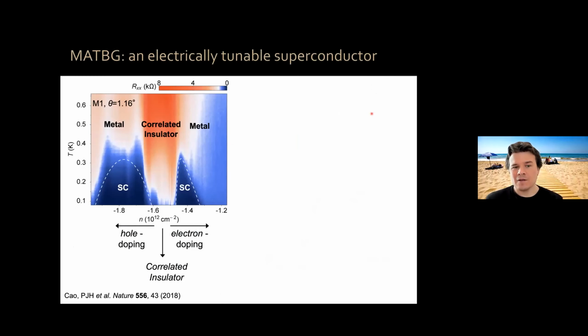Now, magic angle twisted bilayer graphene is an electrically tunable superconductor. In our devices, we have the magic angle graphene, and we have a nearby parallel metallic plate, so that we can make a parallel plate capacitor, and by applying a voltage, change the charge on the plates of your capacitor. One of the plates is the magic angle graphene. One of the interesting things about the system is that you have a correlated insulating state when you put, in this case, 2 holes per moiré unit cell. I'll mention a bit more about this later. And then if you add extra holes, you have a superconducting dome. If you add electrons, so you remove a few holes or you add electrons, you have another superconducting dome for electron doping.